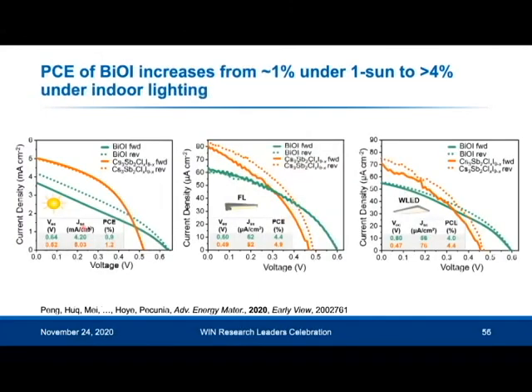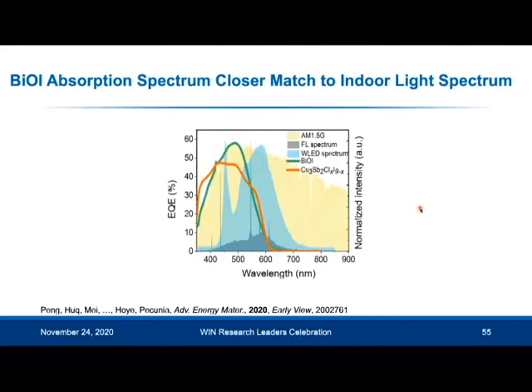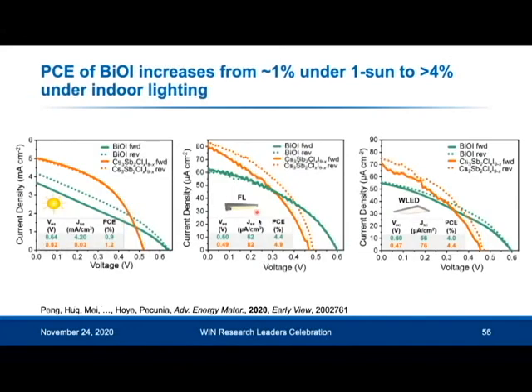So under one sun illumination, they're not very efficient, but under indoor lighting, so fluorescent lighting or white light LED lighting, where the spectrum is much better matched with the EQE spectrum for BiOI, the efficiencies are much higher and they reach 4.4%. And that's significant because currently the industry standard for indoor PV is amorphous silicon, which has efficiencies between 4.4% and 9.2%. So with this first demonstration, we can already achieve efficiencies within the range of efficiencies for the commercial technology.